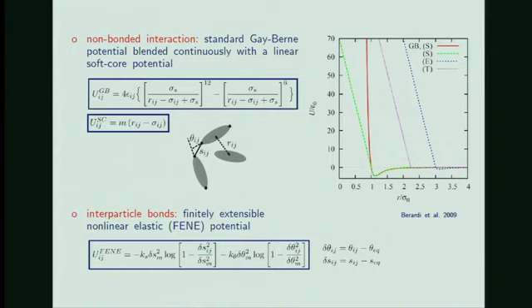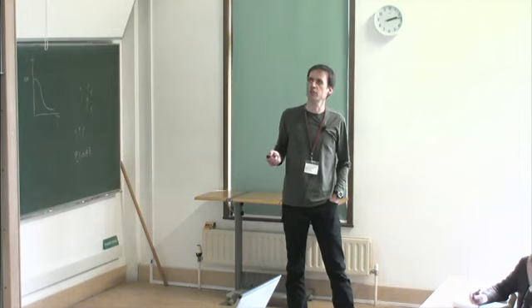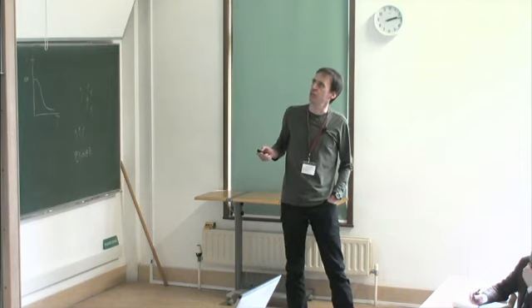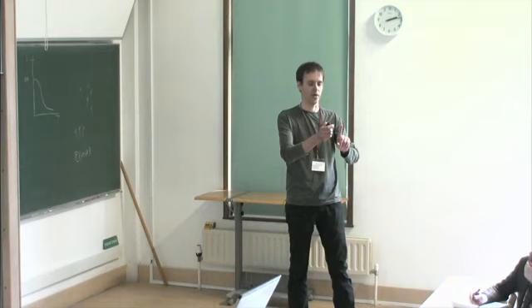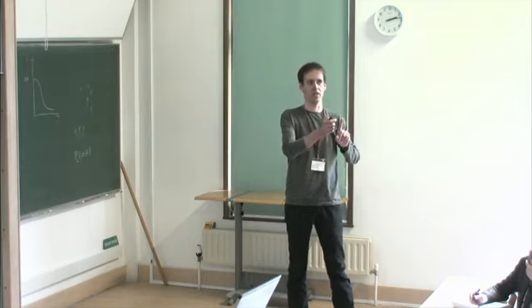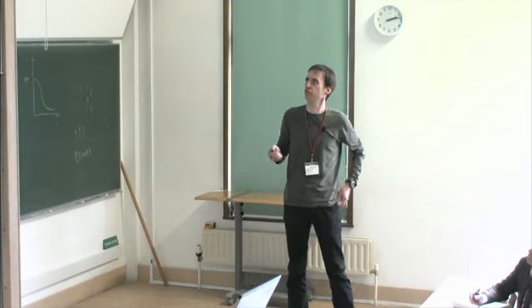So we started with the standard Gay-Berne potential. As you heard in the previous talks, it's basically an anisotropic version of the Lennard-Jones 6-12 potential. But it turned out that the calibration of these systems was rather poor. At the same time, we also learned about this soft-core potential, also introduced a few days ago. And while the standard Gay-Berne would promote pairwise, side-to-side molecular alignment to give rise to nematic and other ordered phases,